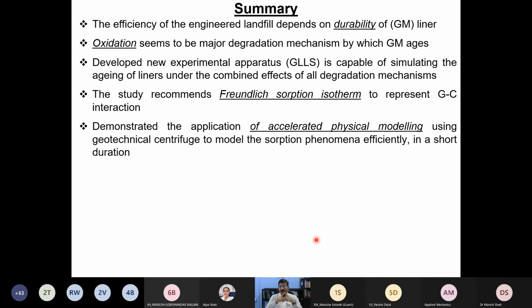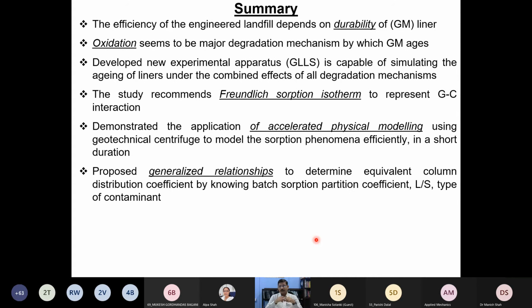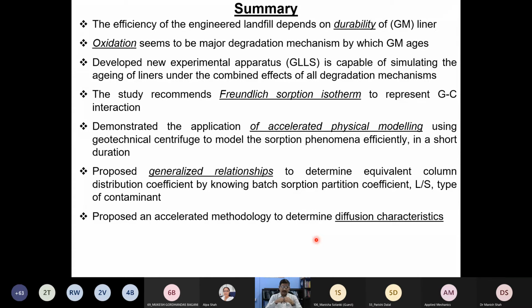And we also demonstrate the accelerated physical modeling by using a geotechnical centrifuge to model the contaminant transport to get the sorption parameters very quickly in a short period of time. We also propose generalized relationships to obtain the sorption parameters by simply conducting the batch sorption experiment, so that you can predict what would be the sorption coefficient when you are conducting the column sorption experiments.